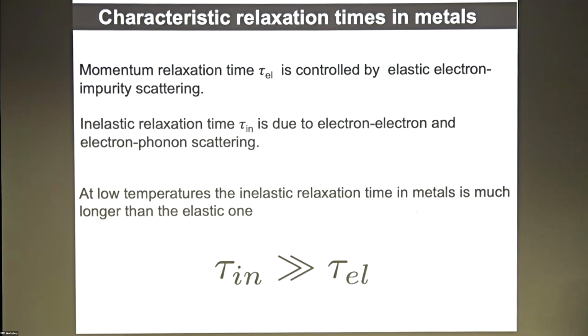And typically in films, the elastic relaxation time is much shorter than the inelastic one by many orders of magnitude. How many? I don't know, and I don't know who knows. It is very difficult to measure inelastic relaxation time in metals. You may think that weak localization gives you information about it, but weak localization measures the shortest of the inelastic relaxation times, and in the Debye relaxation mechanism it is the longest. The longest ratio I know in the literature was from Mikhail, who measured how quickly a metal cools. According to him, this ratio could be 8 or 9 orders of magnitude.